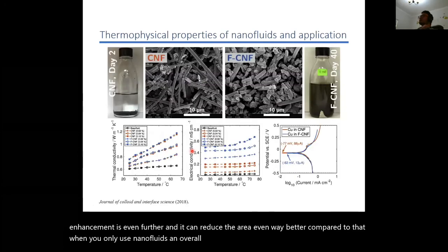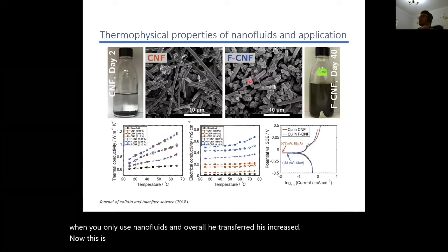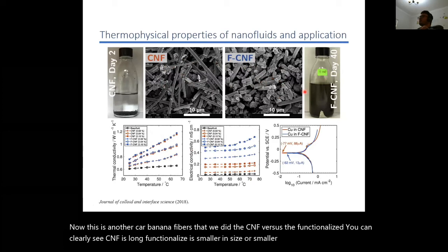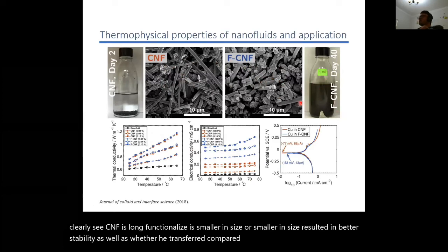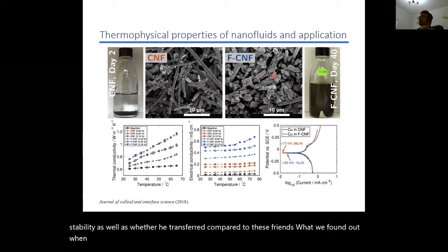Now, this is another one, the carbon nanofibers that we did, the CNF versus the functionalized. You can clearly see CNF is long, functionalized is smaller in size. So smaller in size resulted in better stability as well as better heat transfer compared to these. But friends, what we found out when we were done with the final study is this FCNF is stable even for more than 2 years.